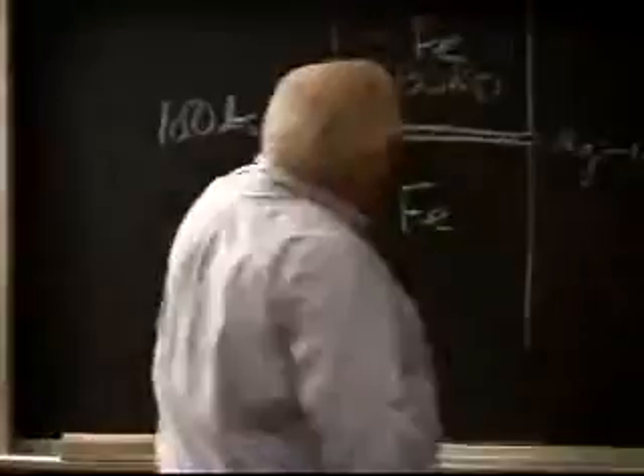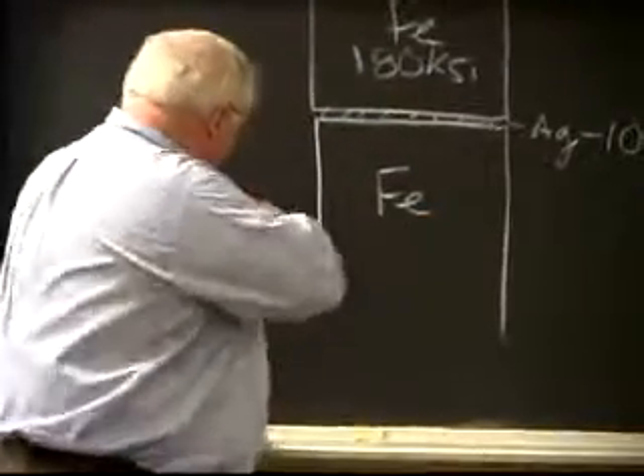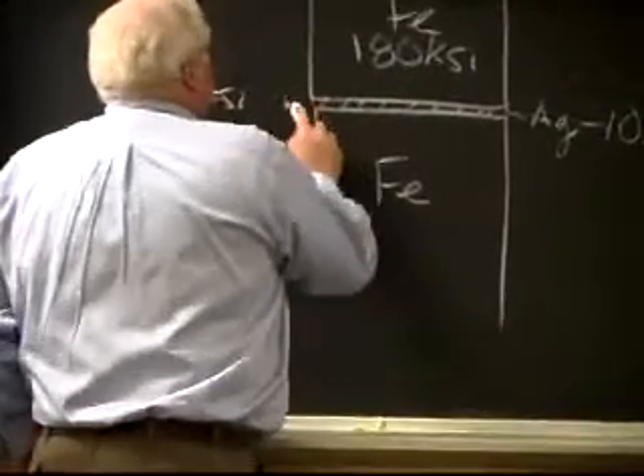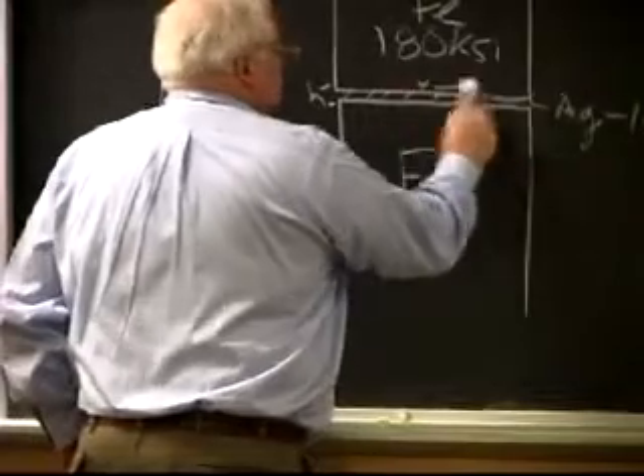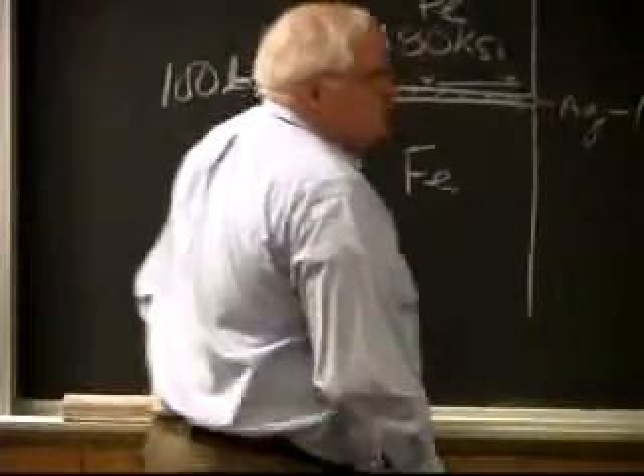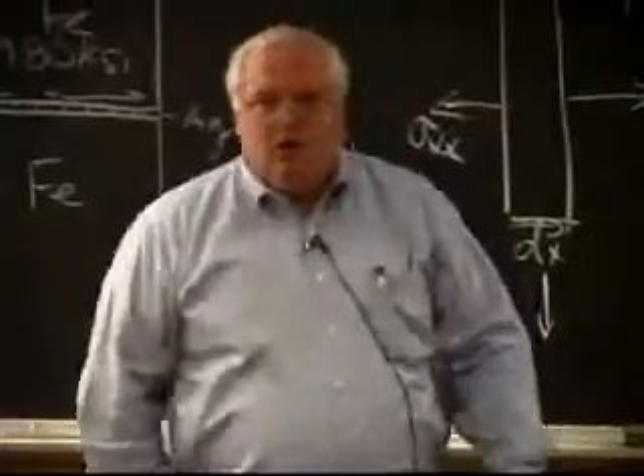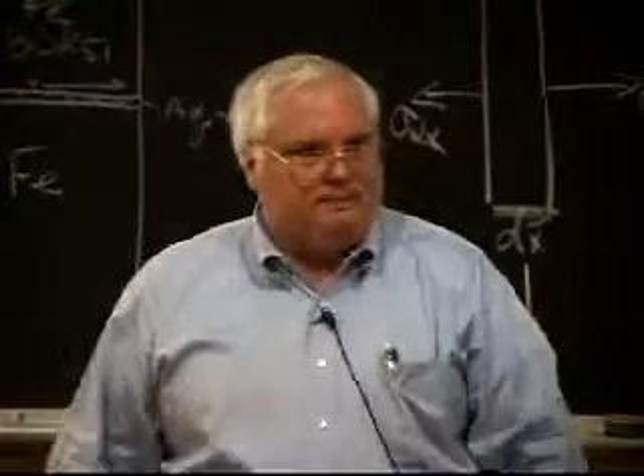Okay? The material can't yield because it has nowhere to go. It's already bound to the material surrounding it. And if this ratio of h to x is large enough, or x over h is actually in the exponential, then you get significant strengthening. Okay? So if the joint is thin enough. And so that's contact strengthening. Braze joints often outperform in thin joints in tension what you would expect them to.